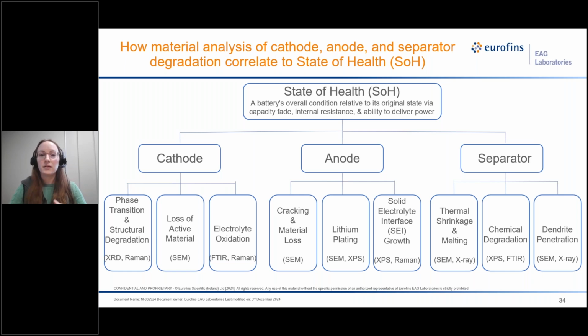And we can see this in our cathode, where phase transition and structural degradation occur. And we can begin to measure this through XRD and Raman. We'd begin to see loss of active material that we can further look into with SEM, or electrolyte degradation with FTIR and Raman. We can also see it in our anode. This would be more of cracking and material loss with SEM, lithium plating with SEM as well, or XPS, and our solid electrolyte interface growth with XPS or Raman.